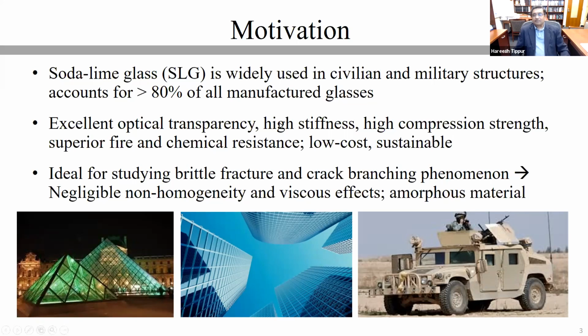It has very high stiffness, relatively high compared to other transparent materials, high compression strength, and excellent fire and chemical resistance. More importantly, it is a low-cost material, and it is a sustainable material. It is also ideal to study brittle fracture, particularly crack branching phenomena. Until now, people had not been able to study this using optical techniques, and that's why they had relied on transparent polymers, which usually have a lot of viscous effects as well as non-homogeneity issues.